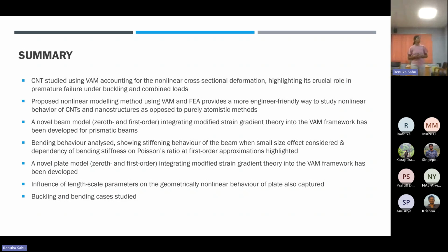A novel beam model incorporating both zeroth order and first order, integrating the modified strain gradient theory into the VAM framework, has been developed for prismatic beams. The bending behavior has been analyzed, showing a stiffening behavior of the beam, and the beam's bending stiffness dependency on Poisson's ratio at first order approximation has also been shown here.